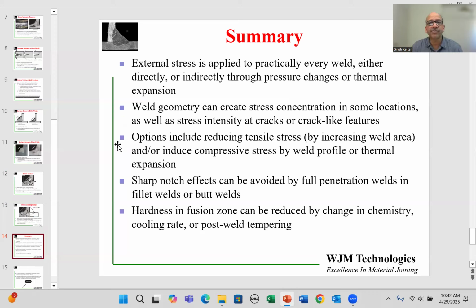Options include, so what can we do? As a design engineer, what you can do is reduce the tensile stress. Now, this can be done by changing the size and shape and profile of the weld, and also to introduce compressive stresses. If you have a positive profile, like a convex profile, when it cools, it's going to have compressive stress. You can avoid the sharp notch at the weld root completely by requiring a full penetration weld, and this can be done with fillet welds as well as butt welds.